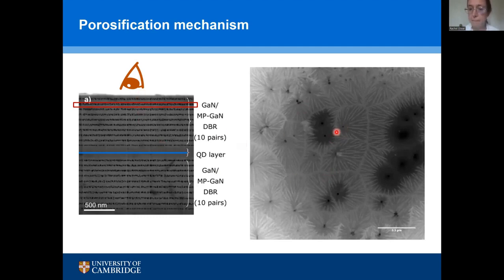We see these little black dots, which are essentially little holes in the gallium nitride, from which the pores, which you here see in mid-gray, emanate. And the remaining gallium nitride, the struts between the pores, are these pale gray or white lines. So it almost looks like the petals of a flower. The porosity emanates from these dark dots out in a sort of circular fashion until the porosity arising from different dark dots bumps into one another, and then we have a boundary between the two, making a sort of domain. So I guess the next question is, what are these little dark dots, these little holes or pipes going through the material? Where are they coming from?